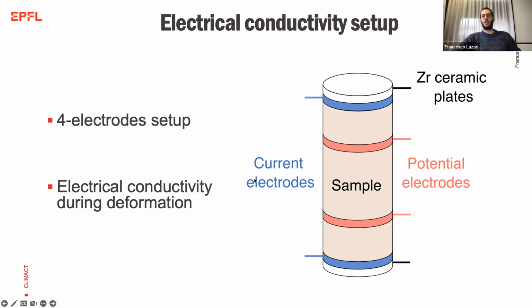So it's a 4-electrode setup, meaning that we impose the current through the sample with 2 electrodes, and we measure the potential difference with other 2 electrodes. In blue, you see the current electrodes. They are 2 copper beryllium alloy plates that are isolated from the machine with 2 zirconium ceramic plates. And the 2 potential electrodes are just 2 stripes of the same metal wrapped around the sample and linked to the instrument and measure the electrical conductivity.